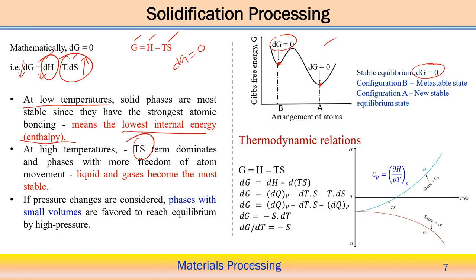Similarly, at high temperature, the TS term is the more dominating factor. If the TS term becomes very high at high temperature, it dominates, and the phases with more freedom of atom movement are favored. That's why at high temperature, liquid and gaseous phases are the most stable, because the TS term becomes very high compared to H. So G depends mostly on the TS term for liquid and gaseous phases, but on H in the case of the solid phase.